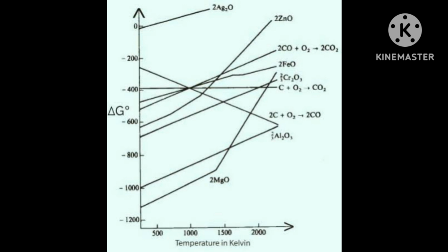Then I have told you two limitations. First, it does not say anything about the kinetics of the reaction, and second, the interpretation of delta G is based on K. Thus it is presumed that the reactant and products are in equilibrium, and this is not always true, because the reactant or product may be solid. This I have discussed as limitation.